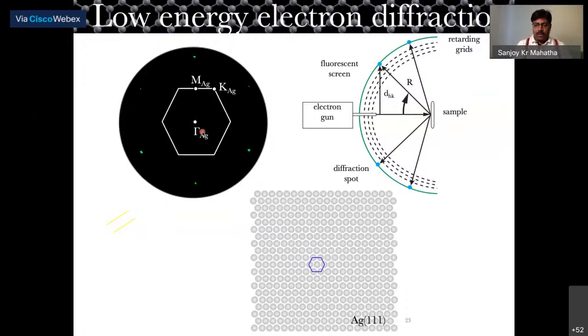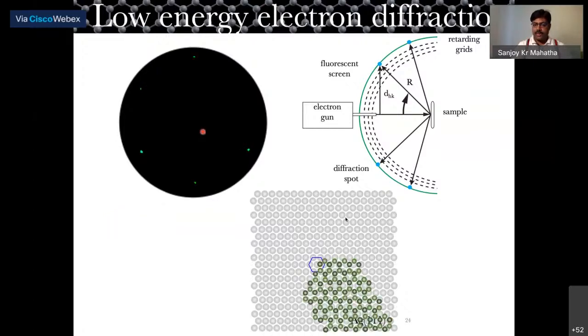And then if we put something on top, for example, let's say we put silicon, which are basically these, and here you can see this also has a hexagonal structure with a bigger lattice parameter, okay, this red one. So in diffraction, in the k space, what we would expect is basically a smaller hexagon. So this is what you would see. So this will be the spot coming from silicene. And then we can also construct the Brillouin zone of that silicene surface.